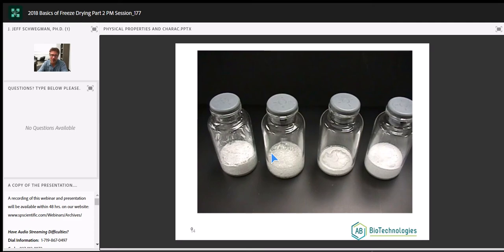Well, when you turn on the vacuum, a very high vacuum in primary drying, you create a situation where that sample will boil at sub-zero temperatures. So that's what's happening. It's boiling, and as it's boiling, it's releasing the moisture. What we have here is what's technically termed a vacuum-dried glass, not a freeze-dried product.